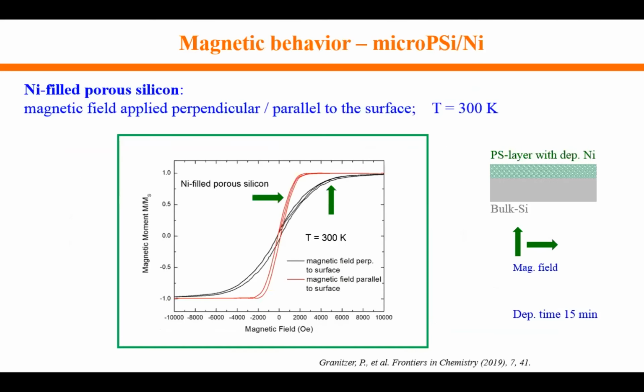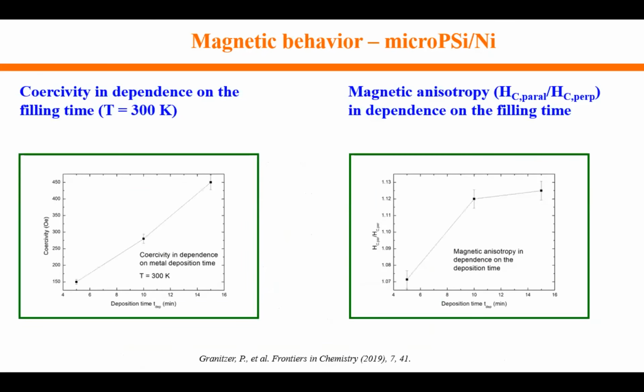So now we look at the magnetic behavior of these structures. We performed field-dependent measurements in two directions with an applied field perpendicular and parallel to the surface. And what we see is that there is a magnetic anisotropy between these two magnetization directions. And what we also see is that the easy axis is for an applied field parallel to the surface. So looking at the coercivity, it increases with increasing deposition time due to more interconnections between the metal structures, and also the magnetic anisotropy increases with increasing metal filling.